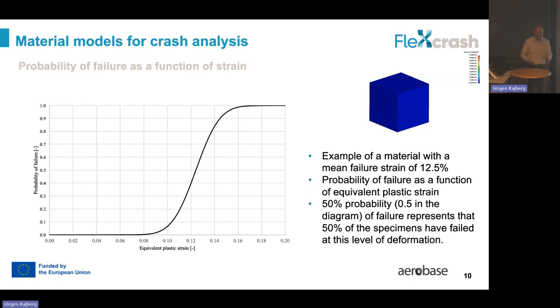In deterministic modeling, you have one value where you get failure, but including probability means that you can calculate the probability of failure. So as an example here on the right-hand side, we have one element. I don't know if the animation is running. No, not. But if you deform this element, on the x-axis you have the equivalent plastic strain versus the probability. So in this case, it's a material with 12.5% of elongation or strain for the mean failure. So you can see when you reach 50%, then you reach this failure strain. At 50% probability, that means that 50% of your specimens will fail when you come to this deformation.